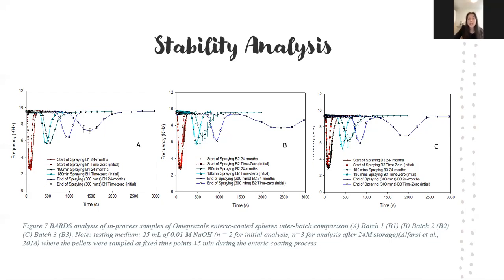Figure 7B shows the analysis of batch 2, and if you look to that navy profile, that end of spraying profile, you see it doesn't actually return to our steady state as it did in batch 1 and batch 3, and that's due to undissolved excipients in our solution remaining in the glass vessel once the run is complete, whereas this didn't happen for batch 1 and batch 3. They were clear colourless solutions at the end of the run. And just a point to note that you can see the F-min of our analysis is steadily increasing with the